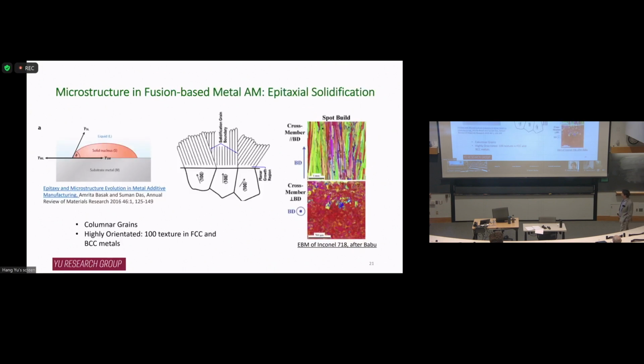Let's first think about how the microstructure forms in the fusion-based AM process. You have a molten pool and you have a substrate. The interface provides heterogeneous nucleation sites. Heterogeneous nucleation is much more efficient than homogeneous nucleation, so nucleation will happen at this interface. The newly solidified material will adopt the crystal structure and the crystallographic orientation of the substrate. Therefore, you're going to have grains grow along the heat flow direction, so you get columnar grains like this. Also, from knowledge of welding, we know for cubic material, 001 is an easy growth direction. So at the end of the day, you always have a strong 100 texture. Naturally, if you don't do anything, you get columnar grains with a 100 texture.